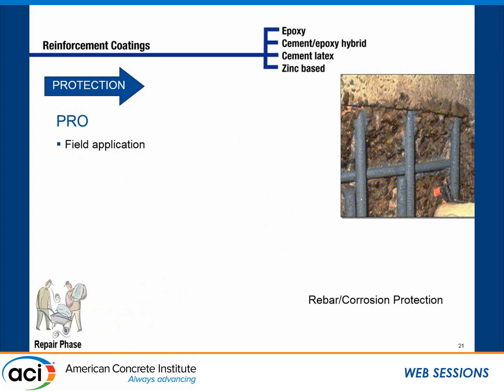Reinforcement coatings can be applied in the field. They're fairly low cost, a pretty mature technology. Some claim to be bonding agents. My personal opinion, even though we sell them, is that a good scrub coat is hard to beat. Have proper surface preparation, take your repair material, mix it to the consistency you'll use, scrub it into the substrate, take the aggregate that doesn't fit in there and get rid of it, and now place your repair material before it dries out.